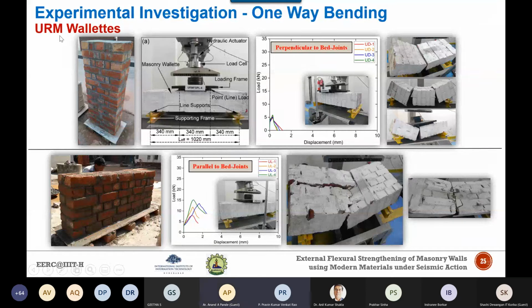We know that the masonry properties are different in its orthogonal directions, and therefore the flexural strength of masonry has been determined perpendicular to the bed joints as well as parallel to the bed joints. Here, in the case of the URM wallettes, we have gone for the 3-point bending test, or rather the 4-point bending test. We constructed a test specimen and laid it horizontally without any compression load, and applied the loading in flexure, in bending. We wanted to see, when we construct the specimen perpendicular to the bed joint and parallel to the bed joint, what orthogonal strength ratio we get.